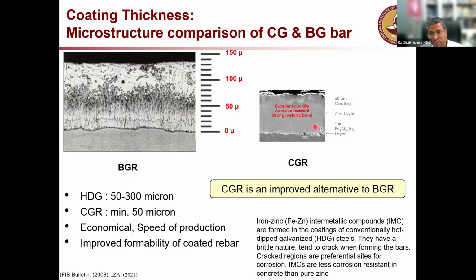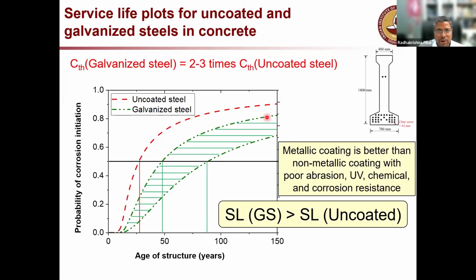So now the industry is coming up with a new product which is called continuous galvanized rebar. Only about 4 or 5 countries in the world are making it today, but I am sure this is going to be the future. You can see a thinner layer of galvanization or thinner layer of zinc, which is actually giving excellent ductility and good abrasion resistance and very good metallic bond with the substrate steel. And on top of all that, because of the zinc, it is very good in corrosion resistance. So this is a new thing which is coming up. And what is the advantage of this? If you go with galvanized steel, there is a possibility that the service life of the structure can increase by 2 to 3 times. I mean, if not service life, at least the chloride threshold will be significantly higher, 2 to 3 times, and an associated service life increase is possible.